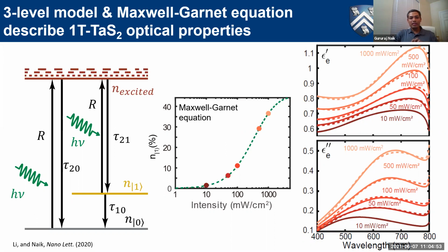When you make the tantalum disulfide extremely thin or sandwich it with different materials, you can change this charge density wave stacking. Actually, in many of these papers, they don't consider stacking as an important dimension in the energetics, just because it was not known before. But some of them show that, for example, superconductivity emerges if you had a single layer sandwiched between two HBN layers. And somebody says, okay, if you had instead of HBN, maybe some other material like aluminum oxide on both sides, you won't see superconductivity. And there are such kinds of discrepancies in many reports.